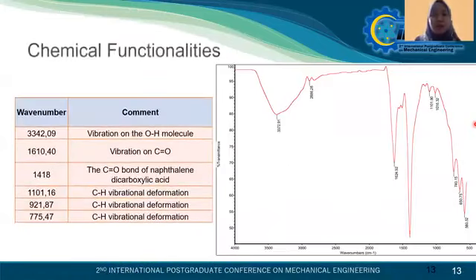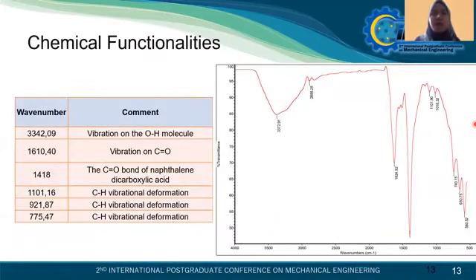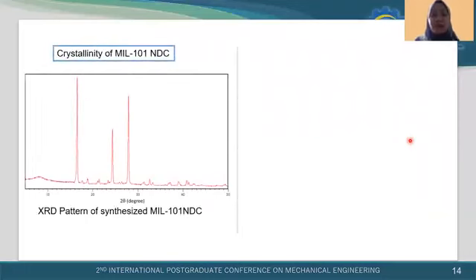And next, here are the results of the FTIR to observe the chemical functionalities. Here we want to observe, is it correct that our MOF contains the naphthalene dicarboxylic acid? As you can see, here are the wave numbers that prove this MOF has been successfully synthesized. And after that, we want to know the crystallinity of the MOF. You can see that the XRD pattern of the MIL-101 NDC has a sharp peak at certain degrees. So it means that this MIL-101 NDC has a good crystallinity.